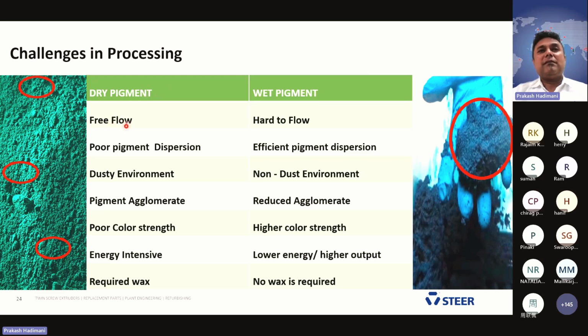Dry pigments are free flowing, but wet pigments are hard to flow, right? You have to use another mechanism to push them into the extruder. It's a feeding mechanism, and we have a solution for that. If you use a feeding mechanism, you can increase your throughput and also lower the SME, the specific mechanical energy. Dry pigments give poor dispersion, and wet pigments give efficient pigment dispersion. With dry pigments, you have a dusty environment, and with wet pigments, no dusty environment. There are more agglomerated particles in the case of dry pigments. Here, with wet pigments, there are reduced or no agglomerates.